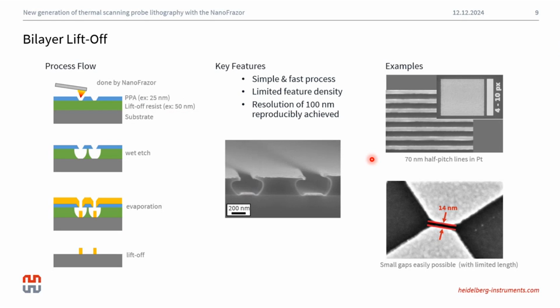For specific geometries, for example, bow tie structures, the undercut plays to our favor and allows us to get much narrower gaps than other geometries. In this example, a 14 nanometer gap. What is particularly useful about this technique is that we don't use any dry etching or oxygen plasma step for the pattern transfer. So the bilayer lift-off method is particularly useful when it comes to patterning contacts, for example, on sensitive nanowires or 2D material flakes.